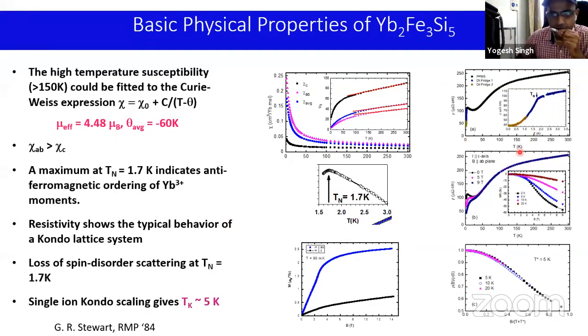There is an anomaly in the susceptibility, which suggests antiferromagnetic ordering at 1.7 Kelvin. Here is the resistivity versus temperature with current along the C-axis, and you see that the behavior is typical of a Kondo lattice compound, where there is a minimum at low temperatures and a logarithmic upturn, below which you get a coherence peak and then a downturn. If I blow up this plot, I see that at the temperature where I saw the susceptibility maximum, you also see a loss of spin disorder scattering. So this is also an indication of magnetic ordering at 1.7 Kelvin.